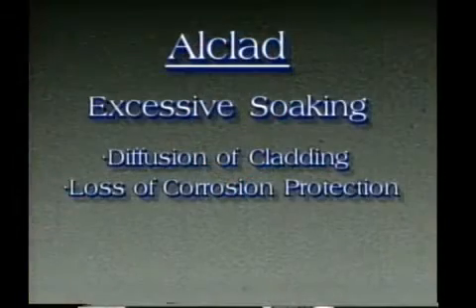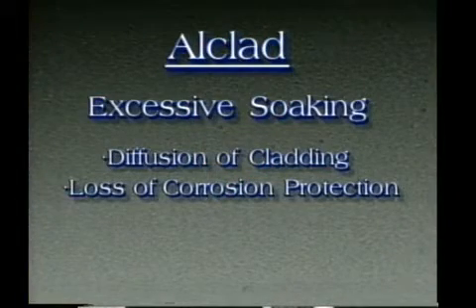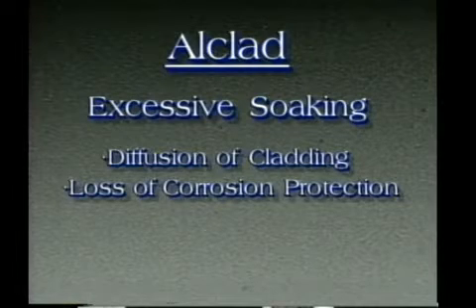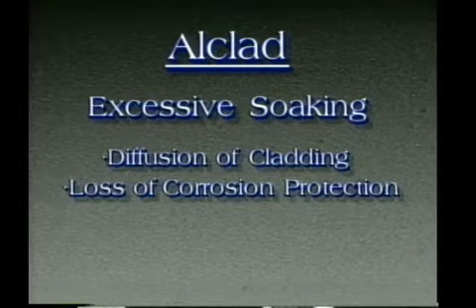treated. In the case of alclad materials, however, excessive soaking can cause the cladding to diffuse within the base metal, and eventually the cladding and the resulting corrosion protection will be lost. To avoid this diffusion, the time of solution heat treatment for clad sheet products must be limited to only that duration needed to achieve the specified mechanical properties. An illustration of the effects of alclad diffusion is shown here. A sample of 7075 T6 sheet, which had been solution heat treated for an extensive length of time, is shown.